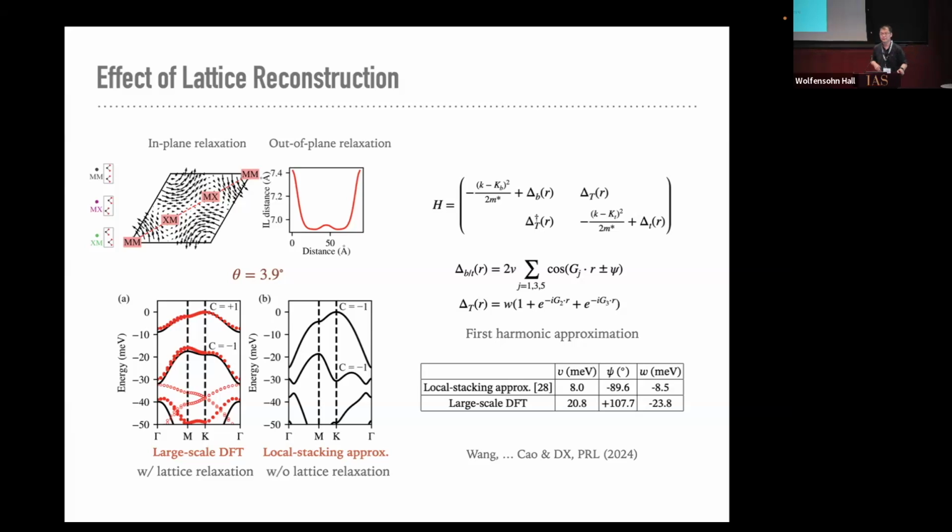Yes, thank you for that question. Those are from the gamma points. Because if you look at the band structure of the TMD across the Brillouin zone, the band edge is at a K point, but the gamma point is very close in energy. Those we have verified are from the gamma points, so we can throw them away.